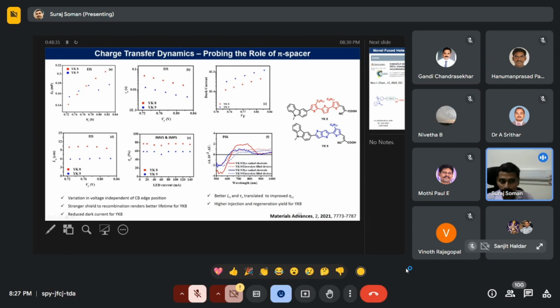There you can see that there is a larger number of excited species present for the YK8 system, which is the red one, which means that the injection is more effective for the YK8 due to the energetics. And then when you add the electrolyte into it, automatically your absorption will get quenched. Why? Because your oxidized dye is not there. Your reduced species, which is present in the electrolyte, supplies the electron, and your absorption gets quenched. Okay, so this is the way in which we work.